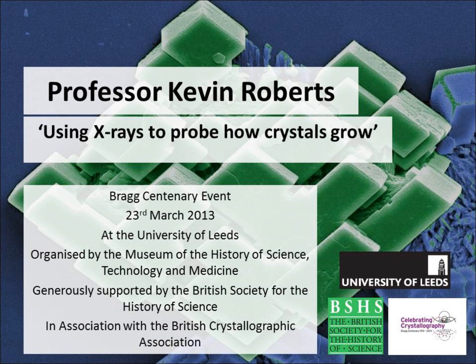This is Viagra, well-known pharmaceutical material, sildenafil citrate. It's a salt with citric acid, and it makes this tablet. The crucial thing in making that is the crystal form. This is what the crystals look like. And in doing that, I have to choose crystals that have the right form to dissolve. It's got to be soluble when you swallow it. And so I have a whole range of materials I have to look at. I might make a salt, I might make a co-crystal, I might make a different form. And to do that, I've got to make sure it's stable, it's soluble, and I can manufacture it.